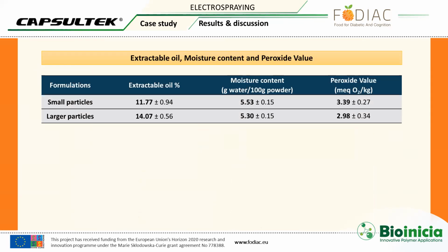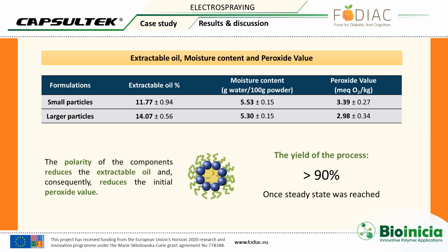Both systems had really good results in terms of extractable oil and moisture content, as the particles were dry, and the peroxide value is in the range of the recommended levels. The yield of the process was really high, so in this scaled system we have reached a processing rate of one liter per hour. So we are now in the range of the food industry, whereas conventional electrospraying technology processes only several milliliters per hour, and is just good for the pharmaceutical industry.